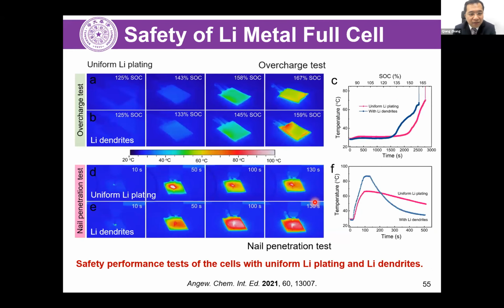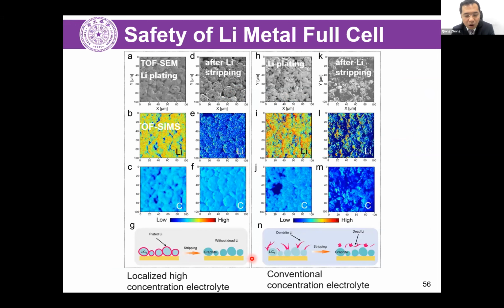And we also test overcharge and nail penetration. It is found that with uniform lithium plating, the temperature rise was not too large. For lithium dendrite formation, the temperature at the tips and edges will be very high. And for the nail penetration test, the temperature rise was also very large. So based on this consideration, we found the importance of uniform lithium metal deposition, in which we try to regulate lithium metal deposition by the electrolytes.